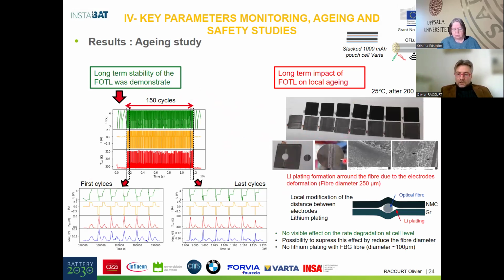You can see here the result of the post-mortem analysis after 200 cycles of the test performed at 25 degrees, and we show some lithium plating around the fibers. We can explain this phenomenon by the dimension of the optical fiber, because the dimension is very big, 250 micrometers for the diameter of the fiber, compared to the size of the electrode. It's a few microns for the thickness of each electrode, and there is a huge impact due to the space here. But this impact is not visible in the global performances of the cell.